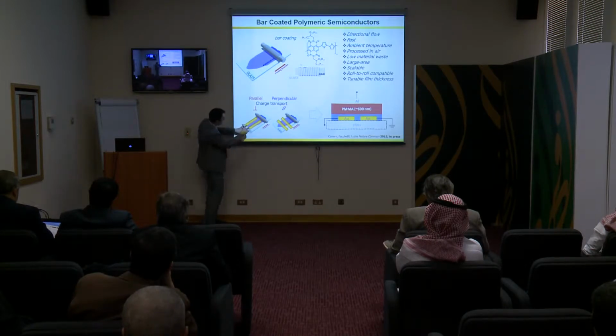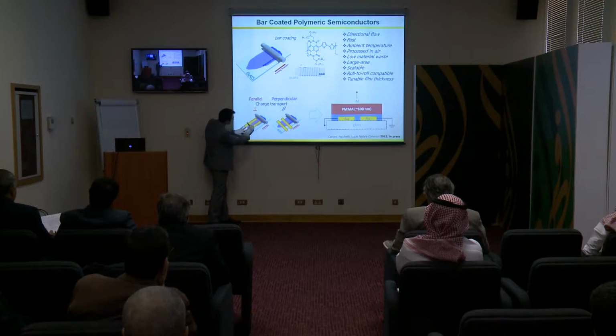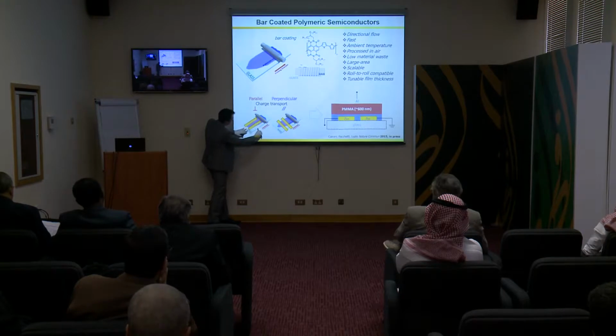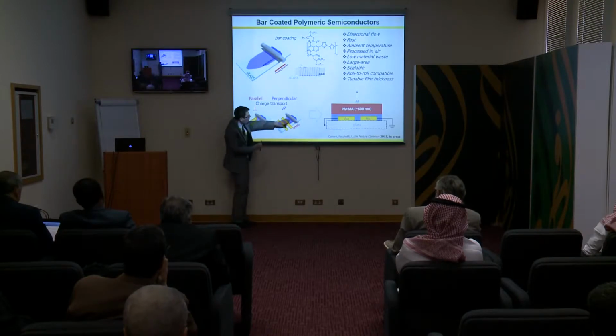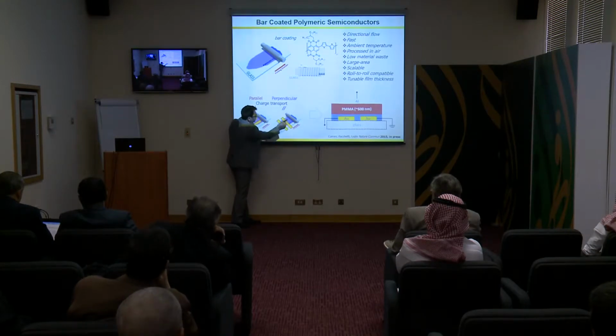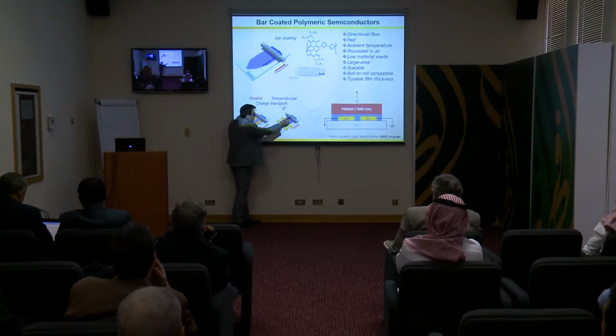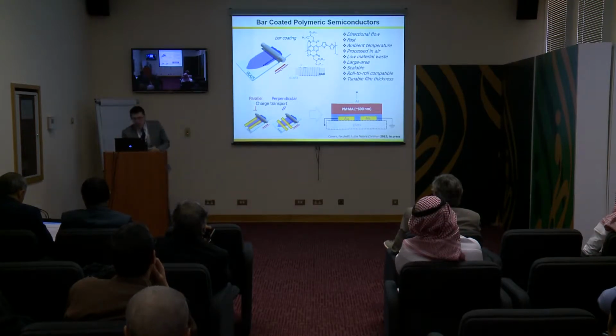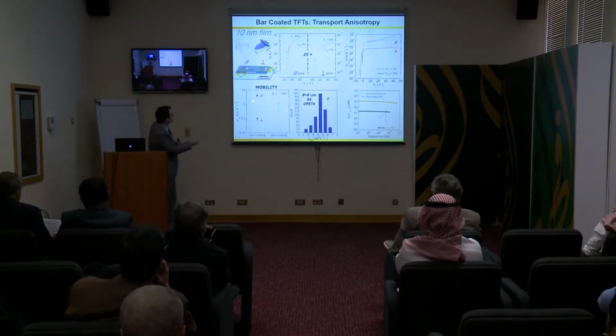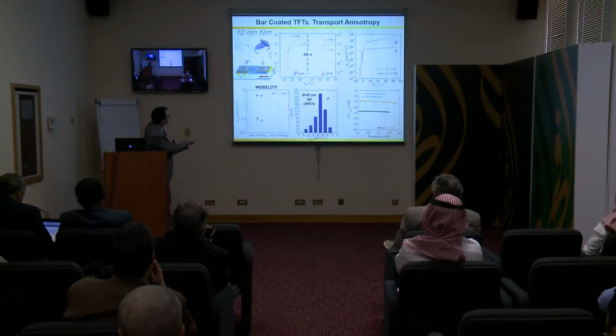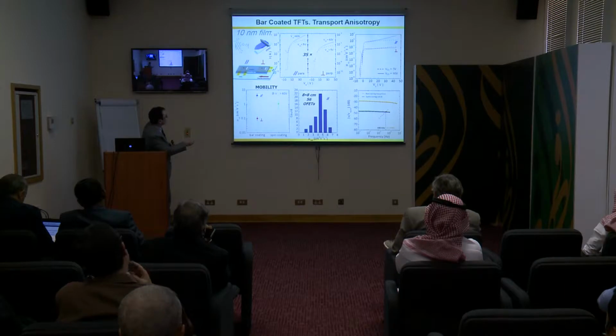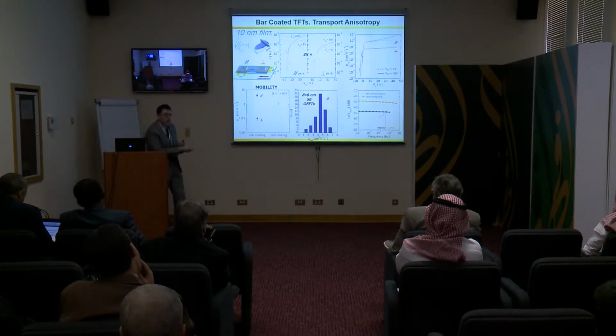this cartoon shows that we can print with this technology. These are the electrical contacts, in the direction of the electrical contacts, which means perpendicular to the charge transport. Charge transport is in this direction, or we can print in this way where the electrical contacts are here. So it tells you that we are printing in the direction parallel to the charge transport. And the results are quite impressive, as if you basically print in this parallel mode, we can achieve mobility which is much larger compared to the perpendicular mode.